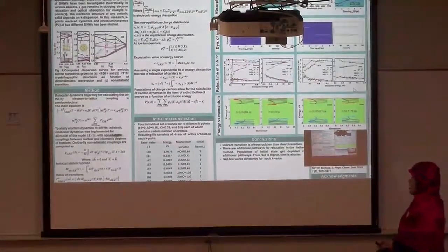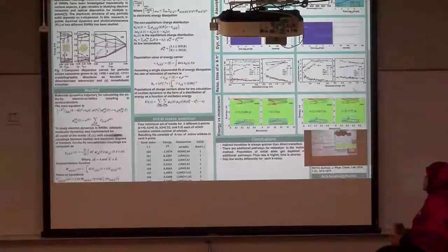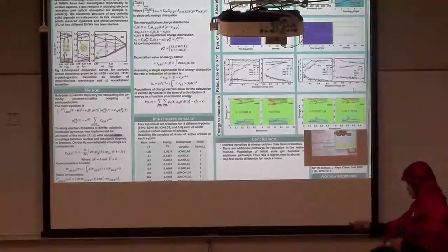Yeah, I understand. So here is the conclusion. We considered momentum restricted transitions and all transitions, which include momentum restricted and unrestricted. In the case of all transitions, our relaxation is quicker compared to momentum restricted transitions, because there are additional channels for the charge carrier to relax to the band edge. That's all. Okay, let's take the next one.